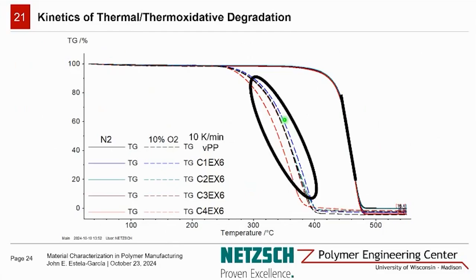When we observe the TGA thermograms for the oxidative results, we observe varying behavior between samples. So this is alluding to differences in the degradation mechanisms and in the polymer stability. These subtle differences can be investigated through kinetic analysis approaches, and these analyses can yield forecasting tools for polymer degradation. And these can then be used to determine optimal temperatures to minimize degradation during processing or maximize degradation during pyrolysis.